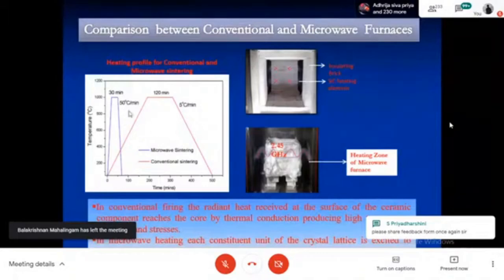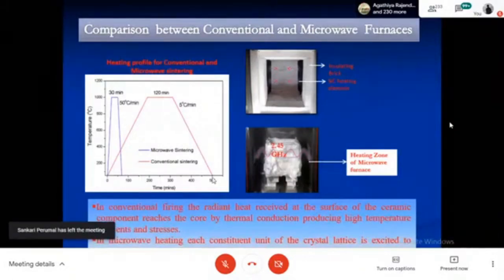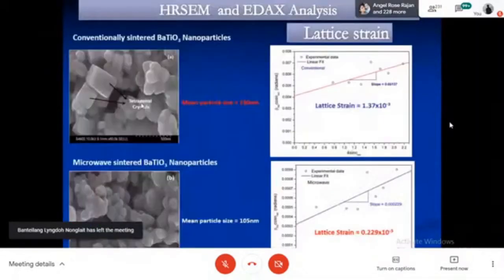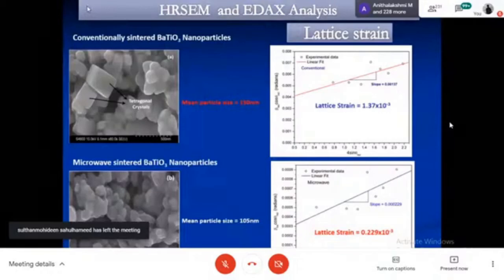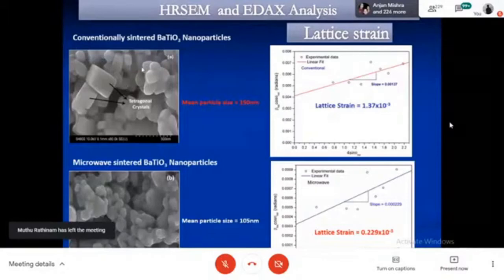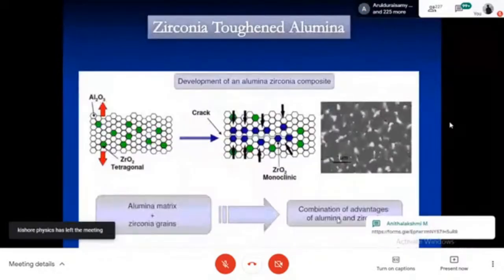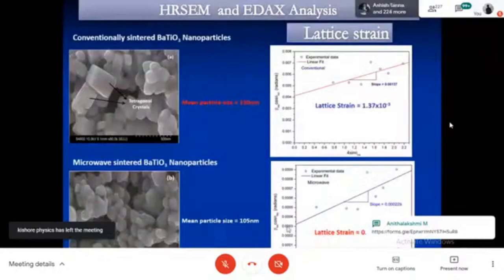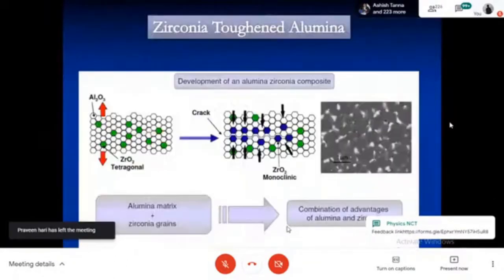For example, if you take conventional heating for a material, it takes typically around 10 hours. And the same process can be completed within 2 hours or within 1 hour by using the microwave synthesis process. In addition to that, the surface uniformity or uniform particle size can be achieved by microwave sintering. With conventional sintering, the uniformity is very, very poor. And also the lattice strain for conventionally synthesized material is very high, and the microwave sintered materials will have very low strain.